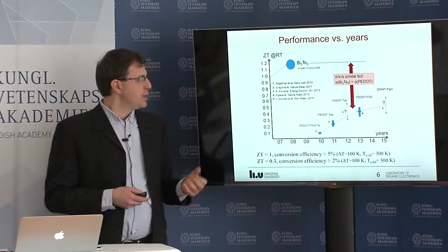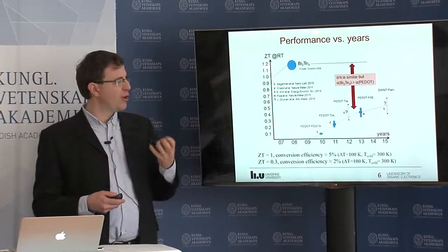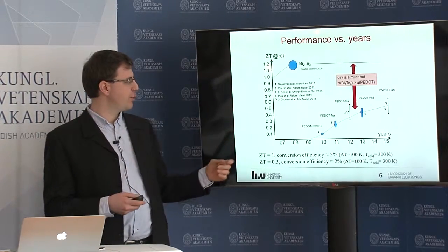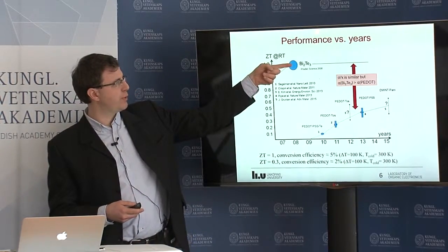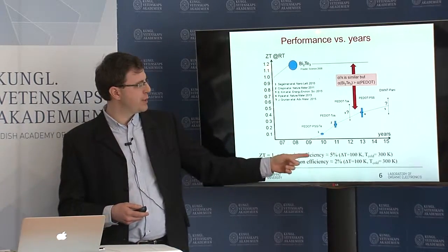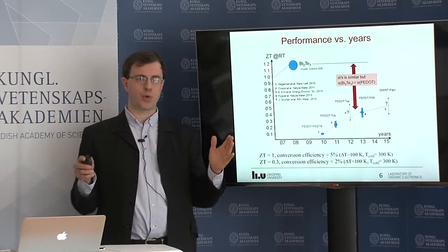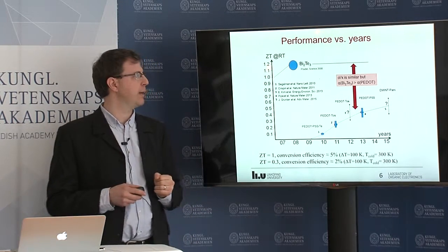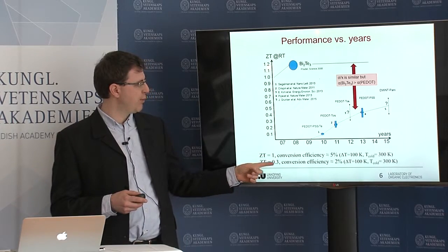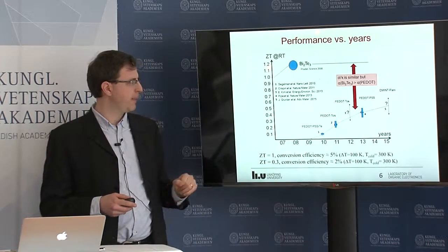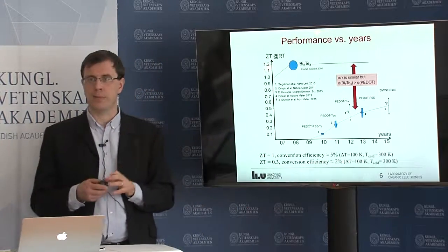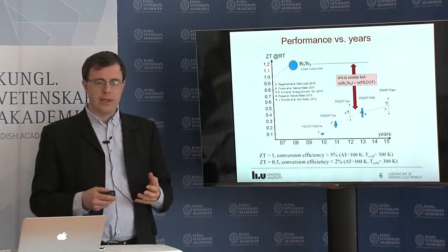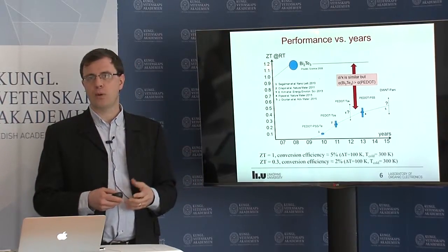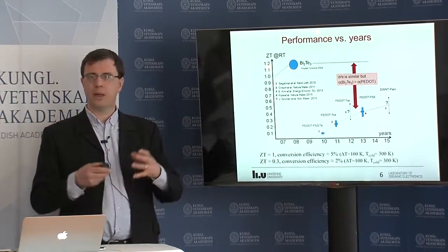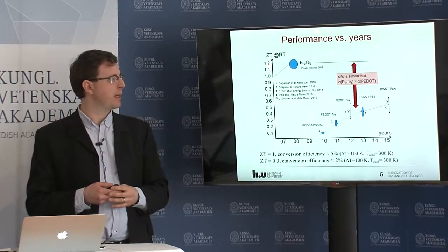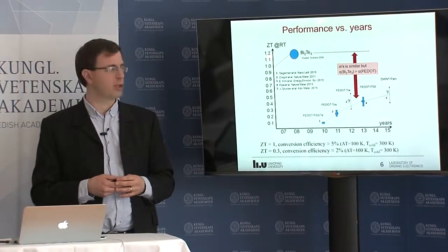And so it's improving, and if we want to have an idea of what it means for thermoelectric generators, for a ZT of 1, so for the state-of-the-art inorganic material, the conversion efficiency is about 5% when you have a temperature gradient of 100 degrees on the material. So if you reach a ZT of 0.3, this is what we have achieved, basically, then we can go to 2% for the same temperature gradient. So it's not that great, but it's improving, and we will see where it ends. I don't know yet if there will be any viable technology based on that material, but it's certainly worth trying and searching a little bit more.